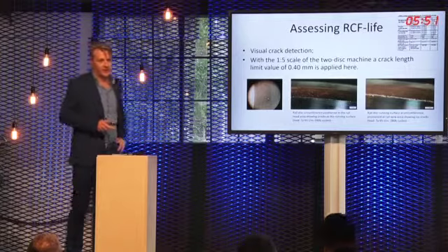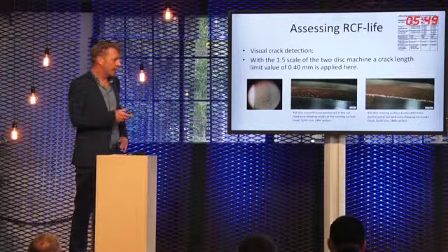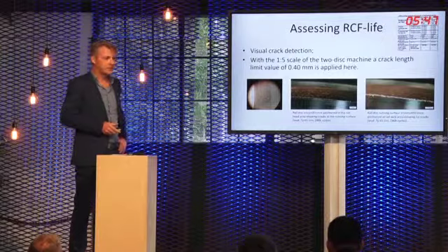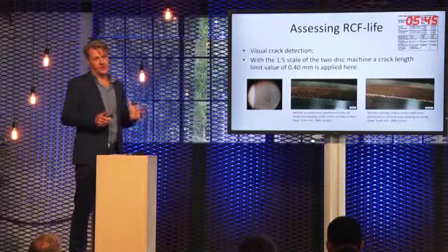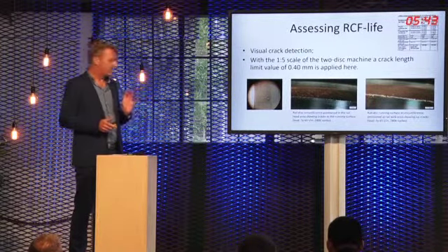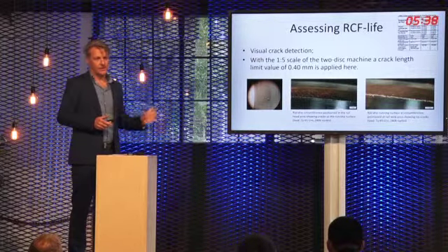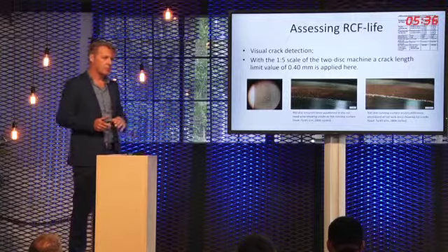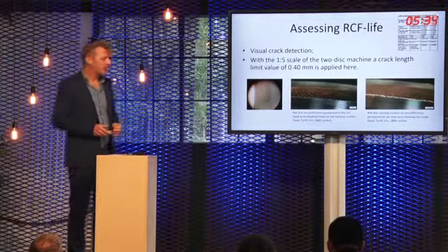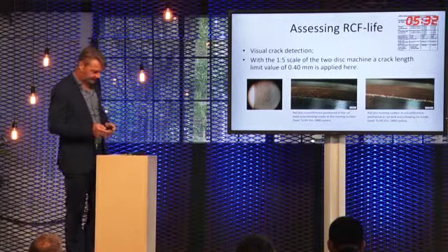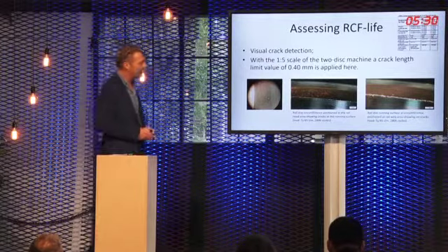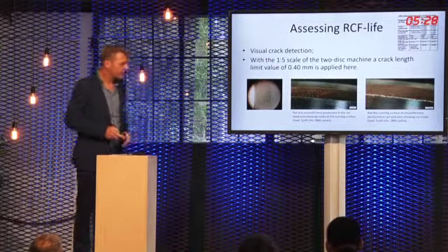What was very striking is that we managed to find rolling contact fatigue development in the part of the rail disc that was machined from the rail head. But in the rail web and the circumferences that was also in the foot of the rail, no cracks occurred. So that was really a first striking difference.